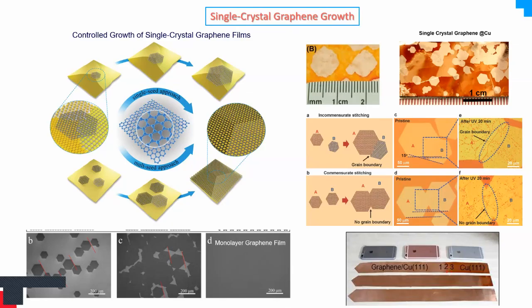If you can control the orientation of the surface in a single direction, then once these individual crystals, which are oriented at the same angle, come into contact with each other, they are stitched together to make a whole film, a single crystal of graphene. So this method is also very interesting and can be used to grow single crystal graphene on a larger area.